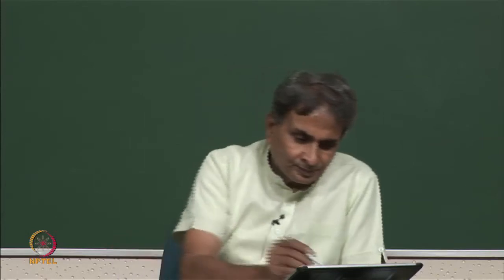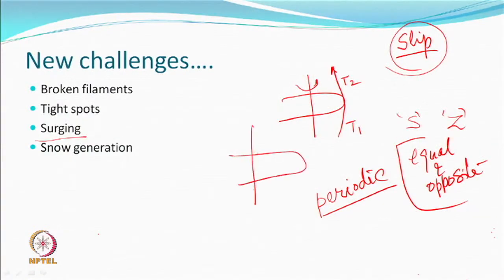spin finish. So, it is absolutely on the surface. Then there are oligomers which may be on the surface. So, when there is slip, this is what keeps on getting removed because of slip and abrasion. One is hard, the other is soft, and this keeps on collecting on the disc surface itself, at least on the top of it. So, you may have some deposits somewhere because of this abrasion, and this is white and so it is called snow.